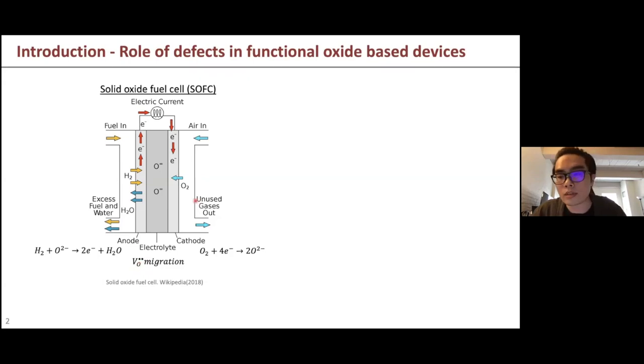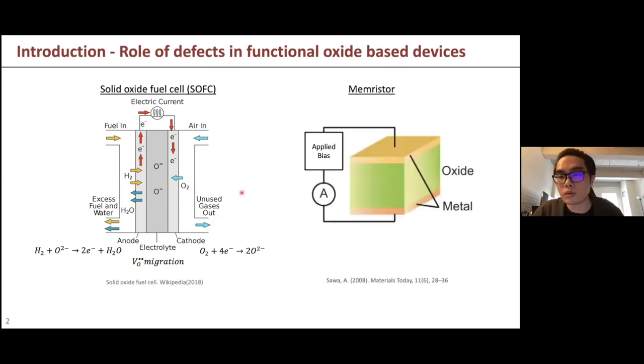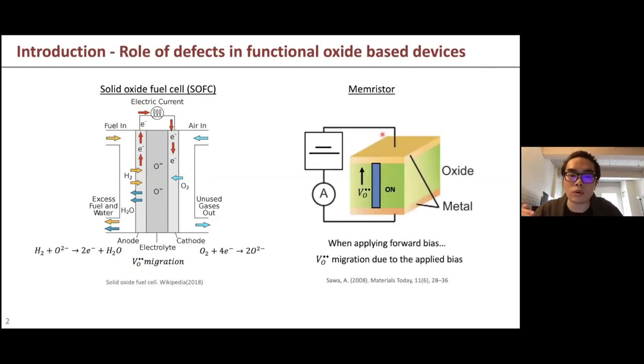And the second thing is the memristor. For people who are not familiar with it, here I'm just showing a very simple example of how it should look. We have two metal electrodes with a functional oxide in between, so it's like a sandwich. When we apply a bias, oxygen vacancies will go in one direction. In this case, they will form a conductive filament and bridge the two sides. Then the conductivity of the whole device is high, so you can see it as a one in the storage device.